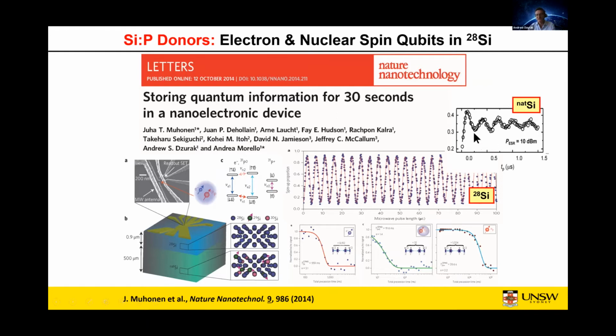Indeed, this idea of using silicon-28 was originally envisaged by Bruce Kane right back in his original paper in 1998. What we did, and this was an important partnership with Kohei Itoh in Japan, was that Kohei provided us silicon wafers that were mainly natural silicon, but which had around 1 micron of silicon-28 coated onto the surface of the wafer. Then we made exactly the same device 2 years after our original qubit operation. Up here on the top right, this shows the relatively poor Rabi oscillations dying off in around 1 microsecond in natural silicon. But here is an electron spin qubit in enriched silicon-28, and you can see that the coherence remains well over 100 microseconds.